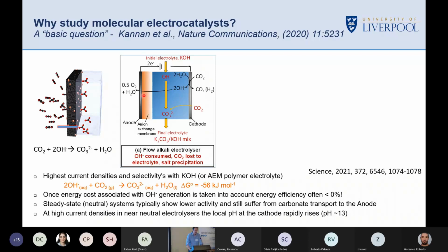The system will probably be using an anion exchange membrane between the two electrodes, and then our carbonate can cross over and go to our anode. And now we've contaminated our otherwise pure oxygen gas stream, so we've lost value there. Pure oxygen has a value, so we don't want to be doing that. So it's generally thought that if we work with a concentrated base, the best we can do in this sort of cell design would be to get about 1 in every 2 CO2s converted, the other one would be lost.